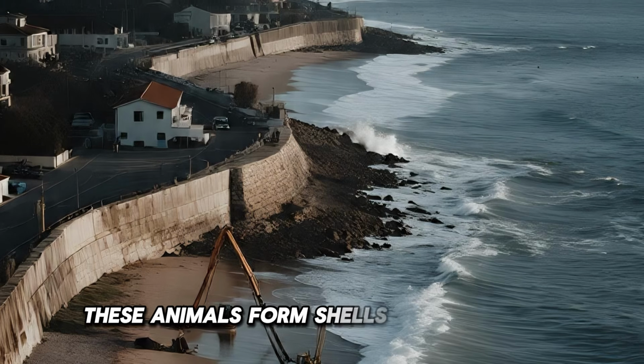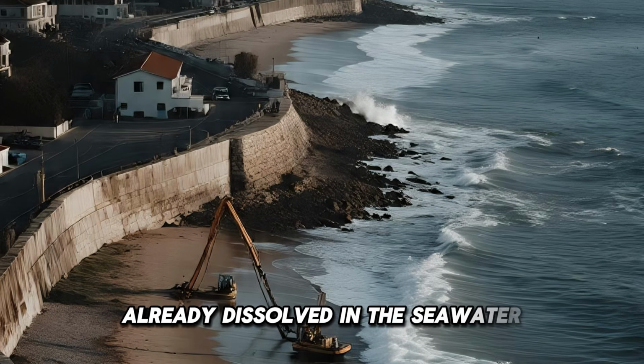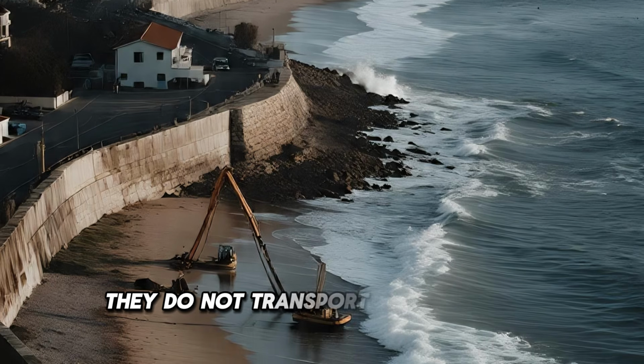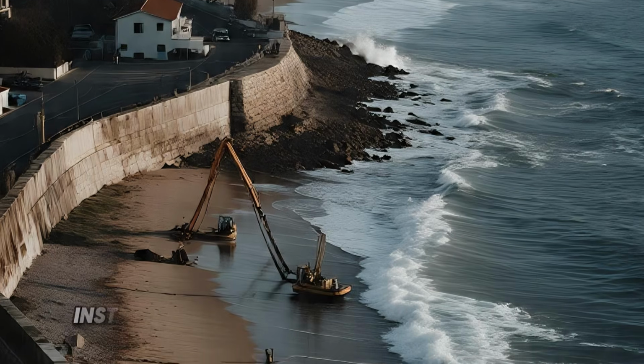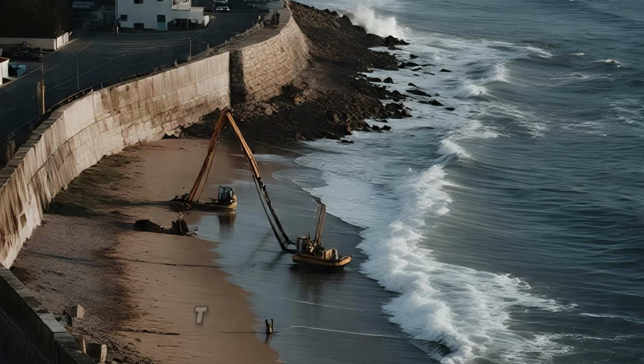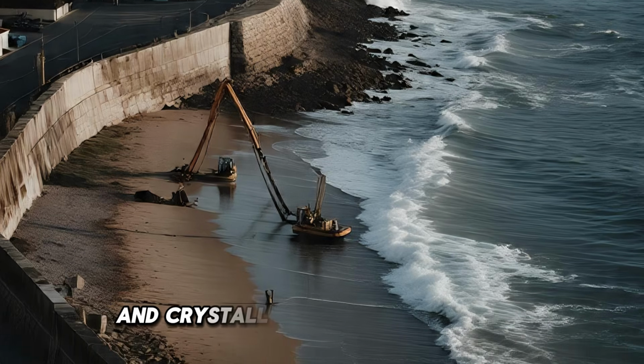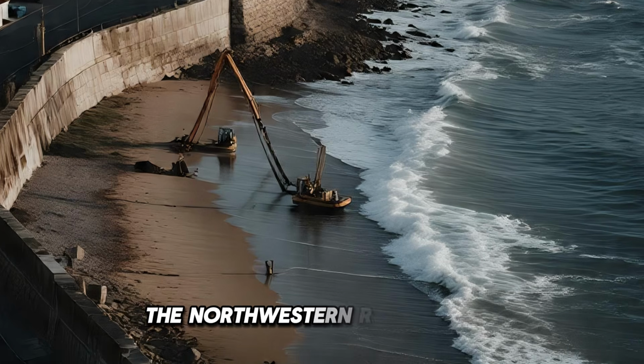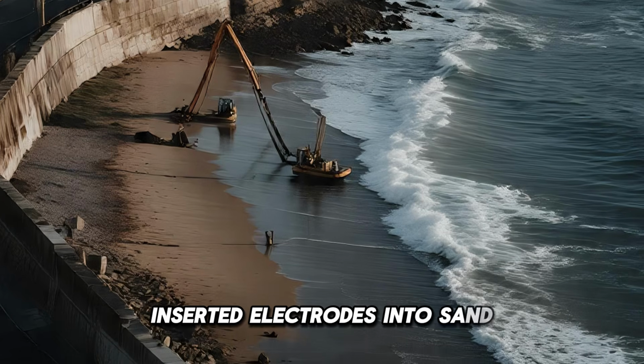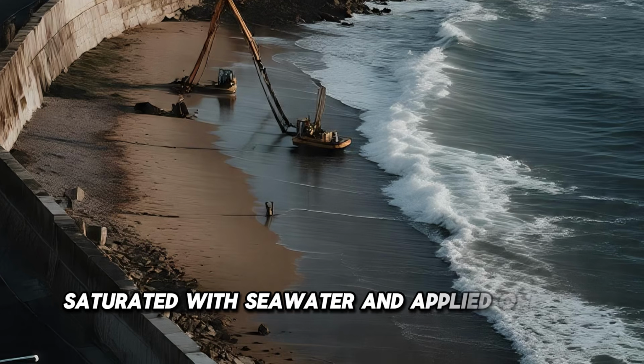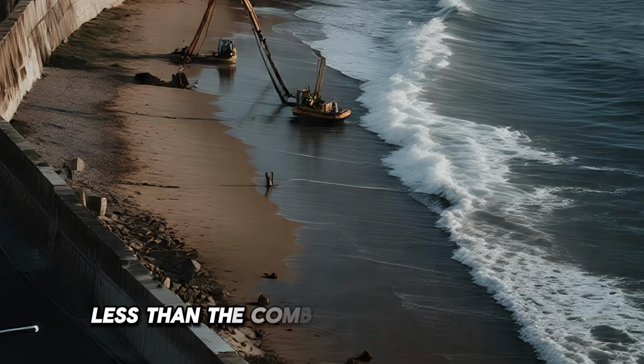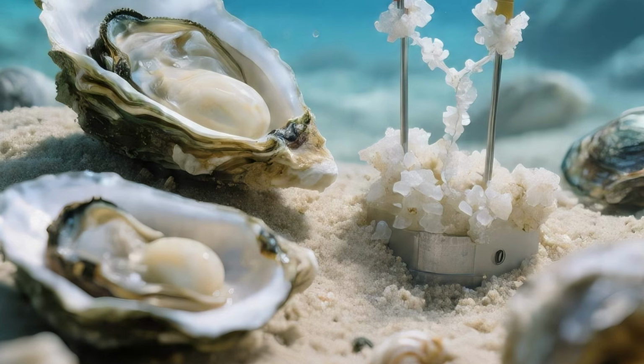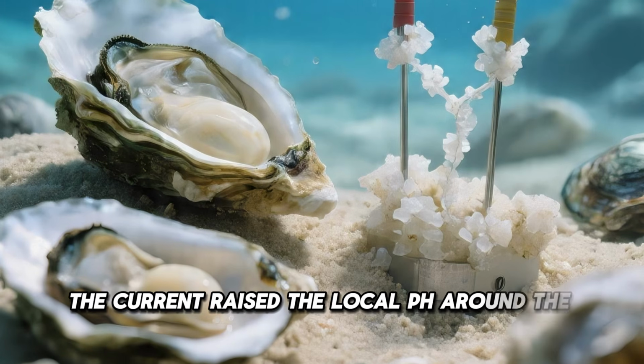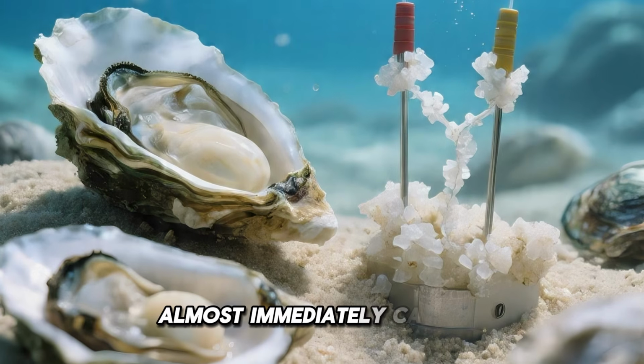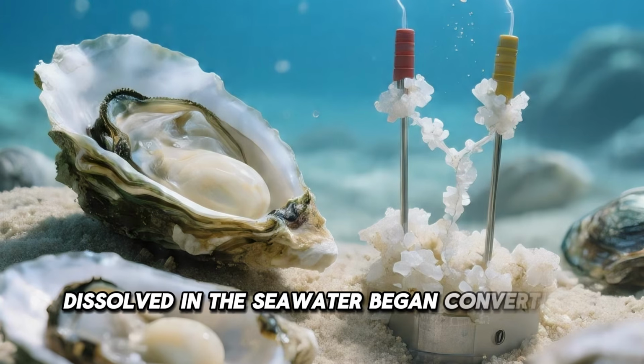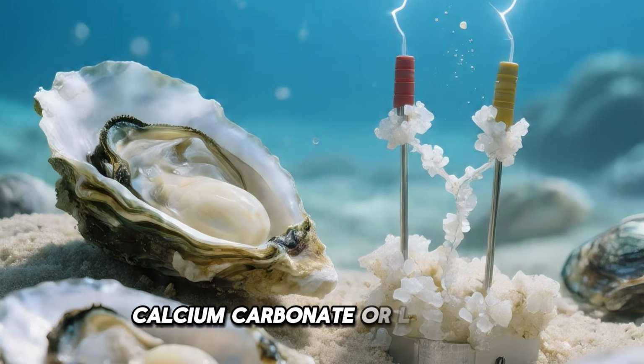These animals form shells from minerals already dissolved in the seawater surrounding them. They do not transport calcium from another location. Instead, they use metabolic energy to raise the pH in a small area and crystallize calcium carbonate. The Northwestern researchers inserted electrodes into sand saturated with seawater and applied only 2 to 3 volts, less than the combined voltage of 2 AA batteries. The current raised the local pH around the cathode. Almost immediately, calcium dissolved in the seawater began converting into solid calcium carbonate, or limestone.